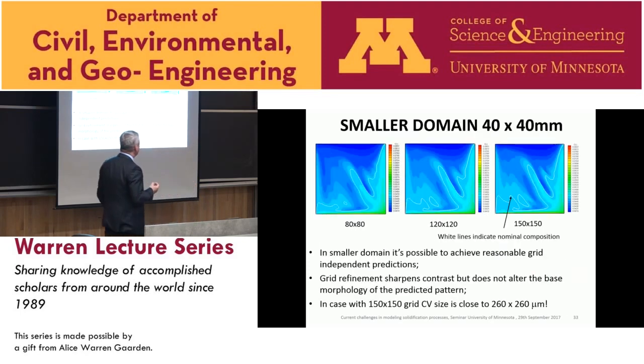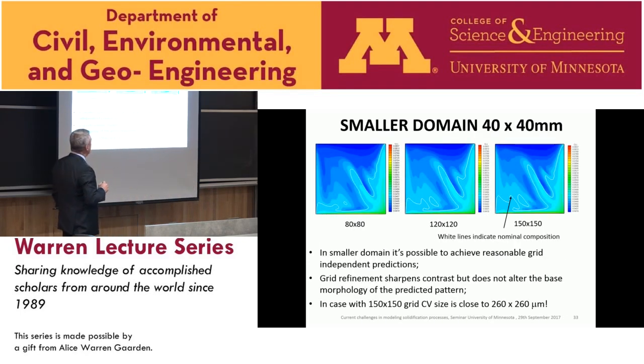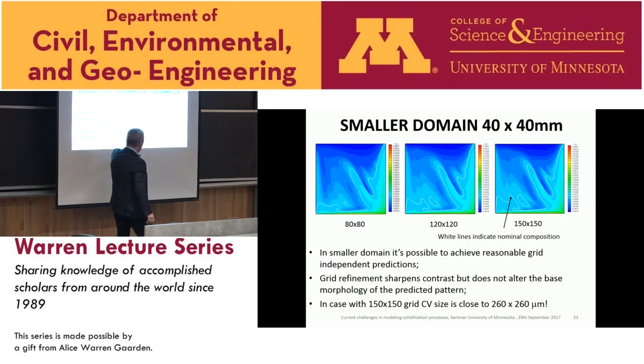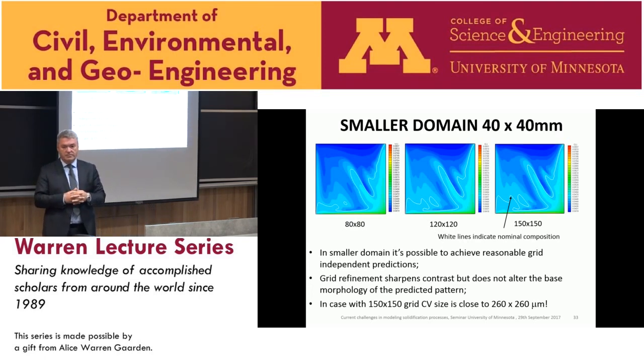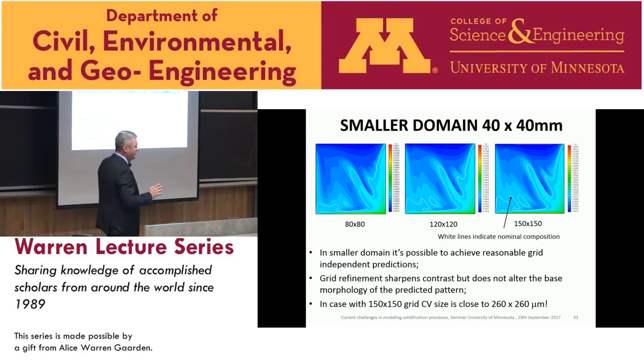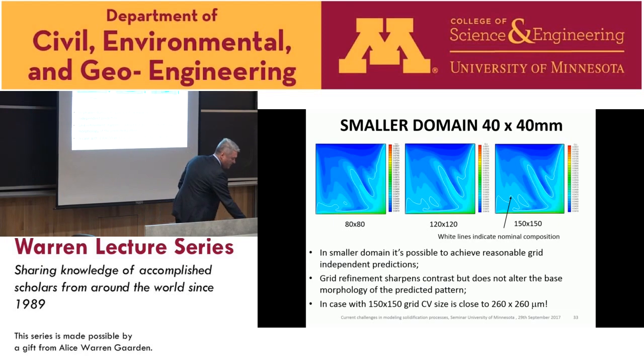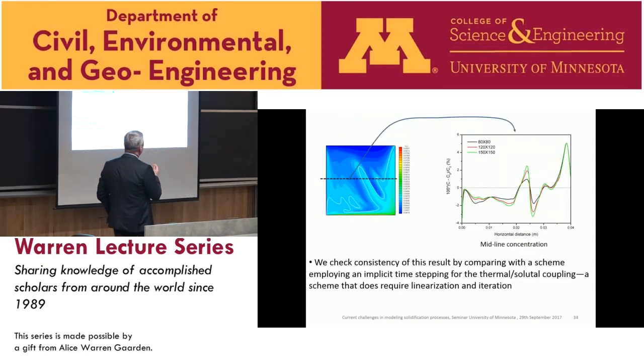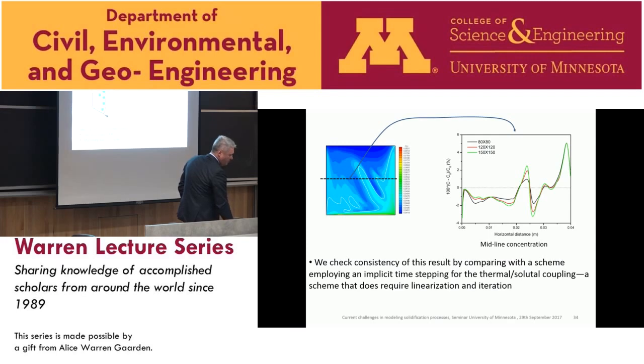Then we tried to change the domain, and we cut the domain in half. Instead of 76, we used 40 by 40. You see, 150 by 150 gives us control volumes of almost a quarter of a millimeter. It's 260 microns times 260 microns. And then we approach the case where our physics doesn't work anymore, because everything we use in the equations is based on a continuum. When you go deeper, into metallurgical details, you can't go so deep. So with the small domain, we achieved grid convergence a little bit. This is the result. We have a sharpening of these results. If someone is interested, I can send you a paper to read about that.